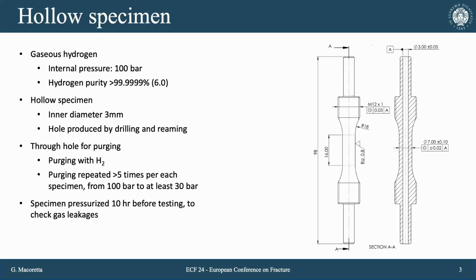The specimen presents a through hole because it's used for purging with hydrogen. So we have a pressure cycle before starting the test. At least 5 times we pressurize the specimen. We release the pressure to at least 3 megapascal, and we pressurize the specimen again, so we don't reach atmospheric pressure, to avoid the entrance of air. And the specimen is pressurized at least 10 hours before testing because we want to be sure that we have no gas leakages before the test. We don't want anything to affect the test because the test is very slow.